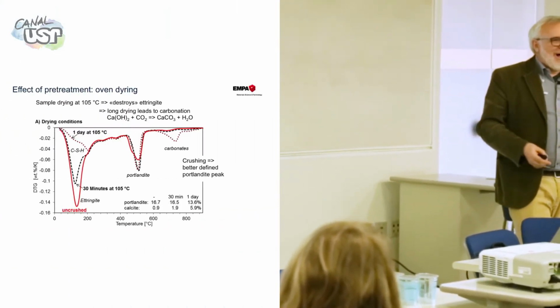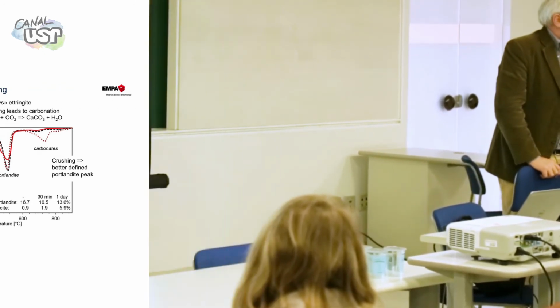Well, oven drying, one day, 105 degrees centigrade. Almost all your combined water with CSH, that is by far the most important hydrated phase in cement, almost all is gone. It's really gone. So it doesn't matter if it is in the ASTM standard or in a lot of published papers. If you want to measure things, you cannot destroy things before measuring them. And the standards have been developed for quality control in real building sites. They are not designed to promote the advance of science. You can do science with good standards, but the opposite doesn't work like that. So never do oven drying.